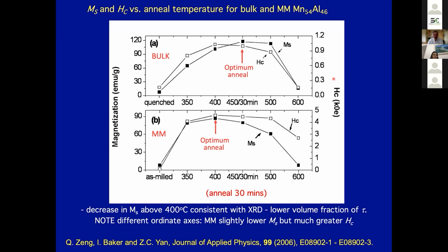This actually shows the saturation magnetization on the left axis and the coercivity on the right axis for bulk material and mechanically milled material. And there's a number of things I want to point out. One is that the optimum anneal to get the best magnetic properties is actually at a lower temperature for mechanically milled material because the transformation is faster. If you look at the saturation magnetization, these two scales are different on the left. The best saturation magnetization you get from mechanically milled is not as good as the bulk material. But if you look at the coercivity, and again, these two scales aren't the same, the best coercivity we get from mechanically milled is far above that for the bulk material.